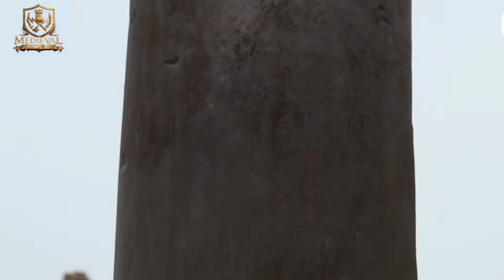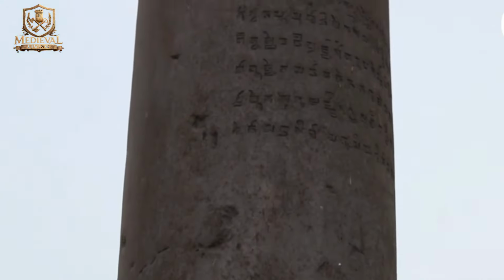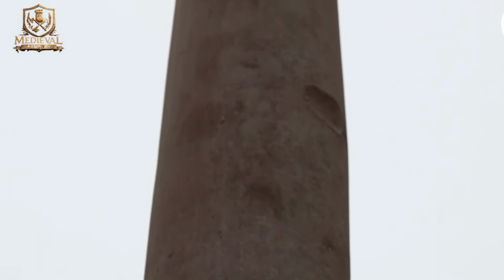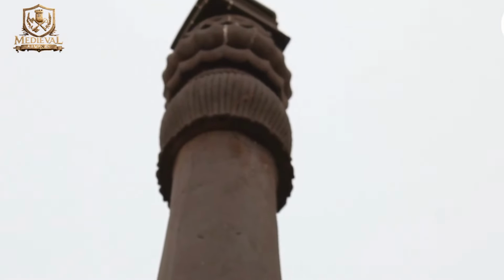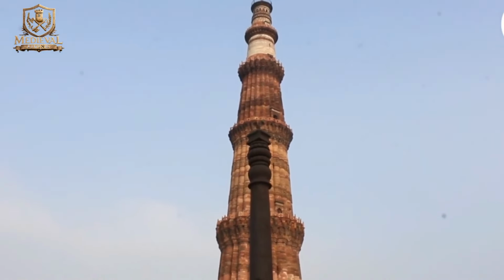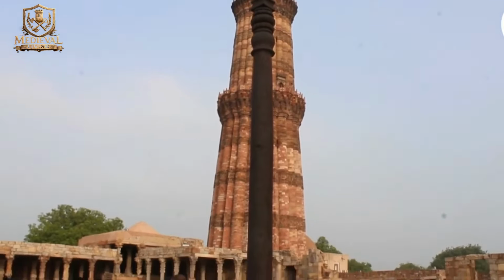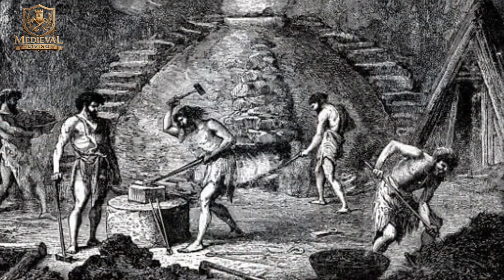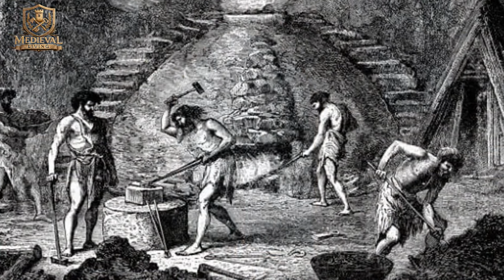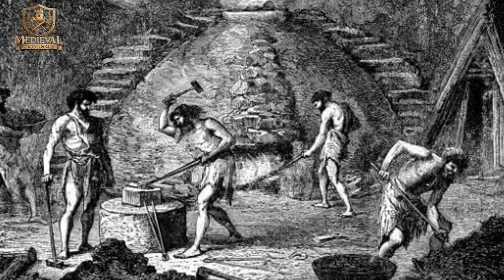It stands over 1,600 years old, weighs several tons, and has remained largely free from corrosion despite constant exposure to the elements. Modern analysis showed that its high phosphorus content, combined with slow atmospheric oxidation, produced a protective surface layer that effectively halted further rusting. Medieval European wrought iron achieved the same effect on a smaller scale whenever phosphorus-rich ore was used.